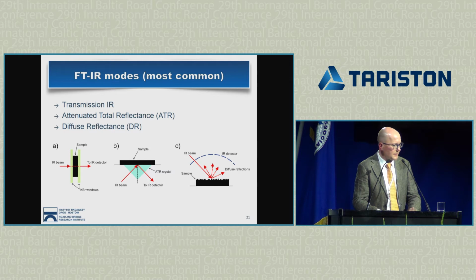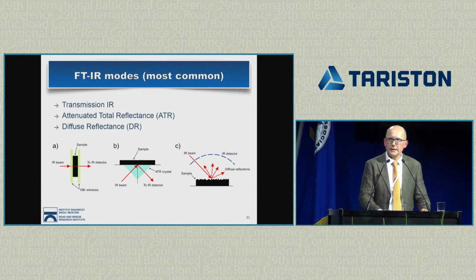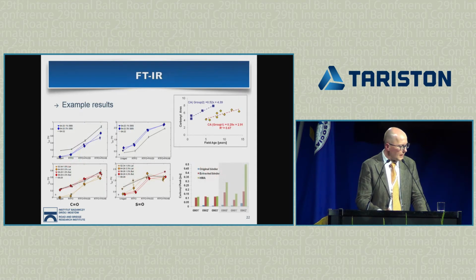And there are a little bit different methods of the IR. I will not go into details of this. You can do it in transmission mode, typically, or attenuated total reflectance, and they are depicted on this figure, and they are also in the paper. Plus, you can use diffuse reflectance. The sample preparation is very simple, at least in the ATR mode. You just put the sample of asphalt, you just stick it to the window, a small window, 2 by 2 millimeter, and you just do the measurement.